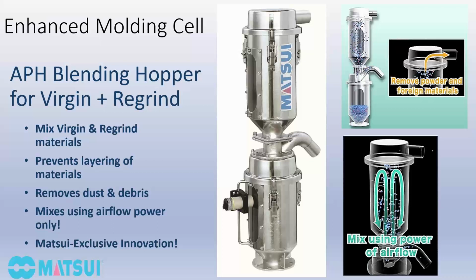So an exclusive Matsui design is our APH vacuum hopper, which mounts directly on the feed throat of the injection machine. The material port is about halfway up the side of the unit, and the vacuum port is on top of the unit. Between those two chambers is a flapper, so when the vacuum is applied, that flapper will seal shut, and it will allow material to be percolated in the top chamber of the vacuum hopper. So that material is being percolated or mixed. It's preventing layering of virgin and regrind material. It's mixing those two materials together. Also, it's percolating the material, giving the material an air bath.